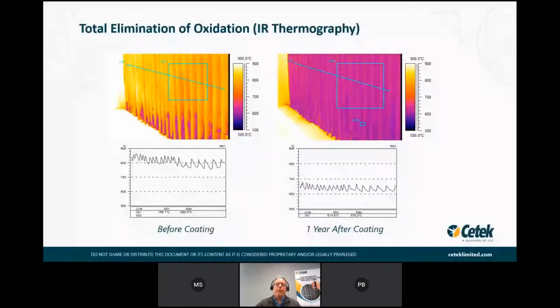On the left, before coating, the heater's been in service for a number of years. You've got a good bit of scale on there, substantial thickness. The thicker the scale, the higher the surface temperature, and the delta here between the tube metal temperature and the surface temperature is about 360 F, call it 200 C. This corresponds to a scale thickness of about 1/8 of an inch, or 4 millimeters.